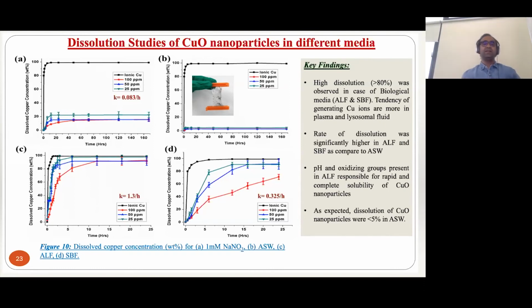But the same particles, when you put them in ALF, which is an artificial lysosomal fluid that mimics the composition of a lung lining fluid, we see that these copper oxide nanoparticles can dissolve completely, to the extent that you're getting 90% to 95% dissolution. Which means that your nanoparticles are actually no longer there. Similarly, simulated body fluid is basically the inorganic composition of blood plasma. Of course, you do not get that high dissolution. You control the rate of dissolution, which is the slope of these lines. But nevertheless, the dissolution percentage is very, very high compared to deionized water and an environmental medium. So which means that these copper oxide nanoparticles can actually act as a reservoir of steady supply of copper ions. Because if you look at the time scale over here, it is in the order of hours.